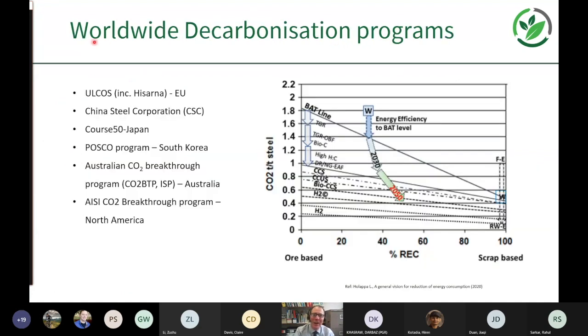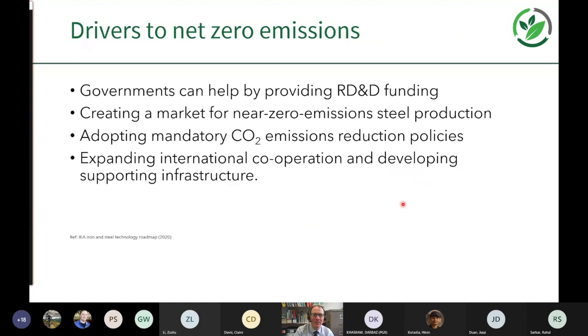And then these worldwide decarbonization programs that I've listed on the left there, the ore-based higher specific carbon dioxide intensity products and processes, they're driving towards changes in the blast furnace: top gas recycling, oxygen blast furnace, using biomass, using carbon capture, using hydrogen to drive down the CO2 produced per ton of steel. So the trend is from where we are currently with the worldwide average to utilize more scrap-based production and to move this down to a lower specific CO2 production per ton of hot metal.